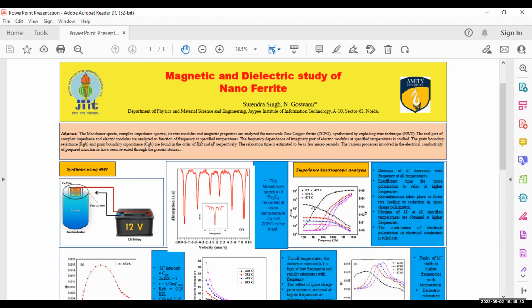So then we did impedance spectroscopy analysis, and here we could see a decrease in the real part of the impedance, which decreases with frequency at all temperatures that we have studied. This is because of insufficient time for the space charge polarization to relax at higher frequencies. There is a mismatch between the frequency of the supplied AC energy and the oscillation of the charge carriers within the material.